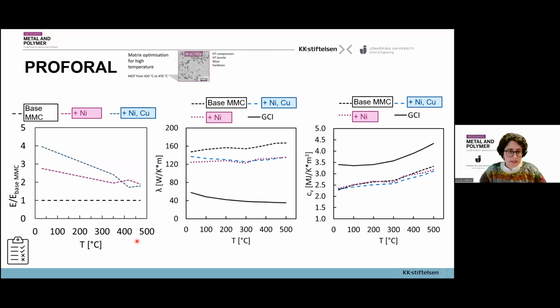So we checked the mechanical properties as said, and we also evaluated the elastic modulus to confirm this higher stiffness related to nickel-based phases. We also checked the thermophysical properties because, as said, that is also a critical point to look into for brake disc application. So we confirmed that even having these secondary phases, we have a slight decrease of thermal conductivity compared to our material, from around 160 to 120, but still the value is more than double what we have for gray cast iron. So it is a compromise that we can accept in this case, this decrease in thermal conductivity. And volumetric heat capacity instead is not affected in this case.